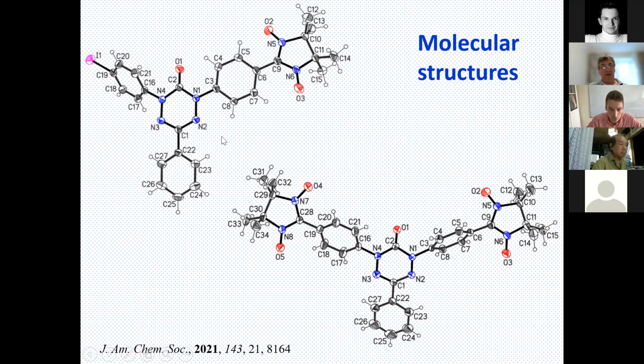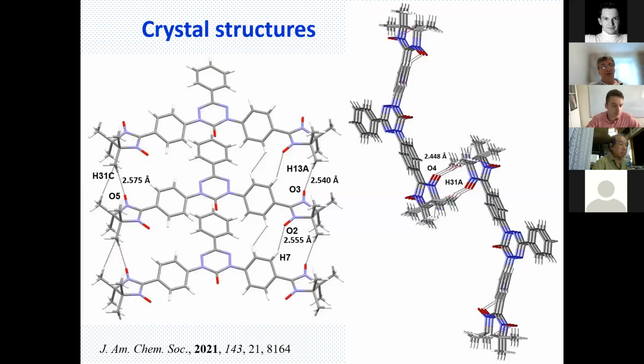We successfully found a solvent from which we succeeded in growing good crystals of di- and triradicals. It appeared that from acetone it's possible to grow good crystals, and we solved the molecular and crystal structure of both compounds. Also, we thoroughly analyzed the crystal structure of both compounds. I will show you the analysis for the triradical.